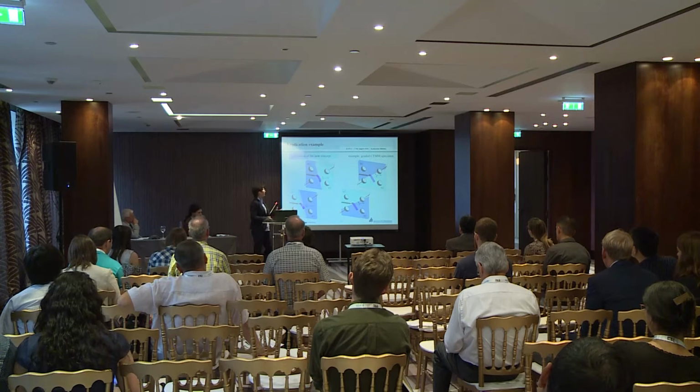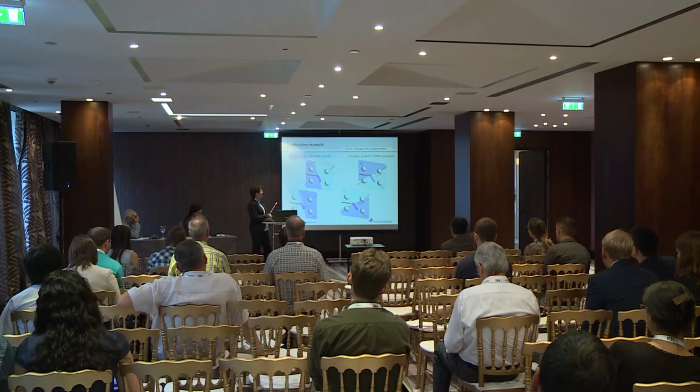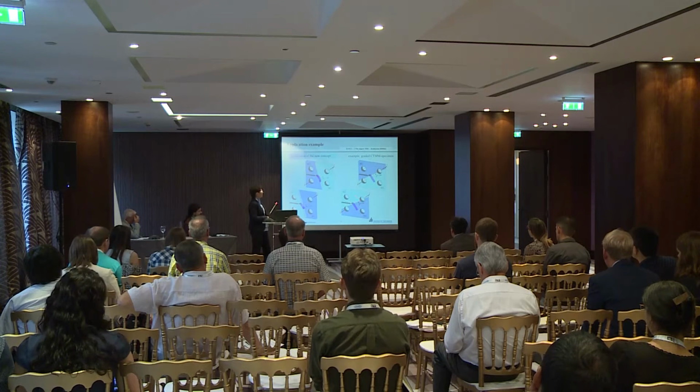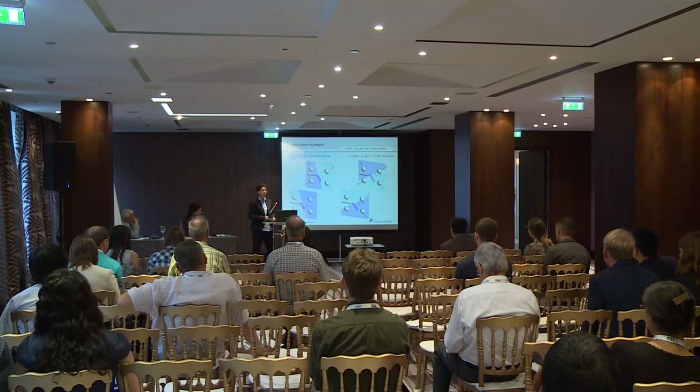Obviously, I tried something different. I changed the local transition angle. Here I had minus 75 degrees. This one is 30. And now you can see, even though I changed the local area properties, there's no influence on the crack path at all.